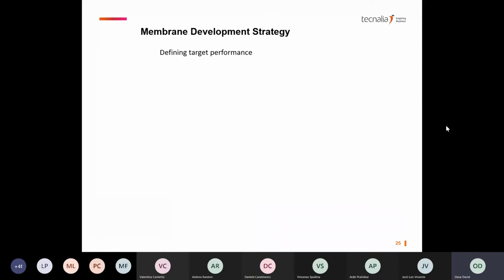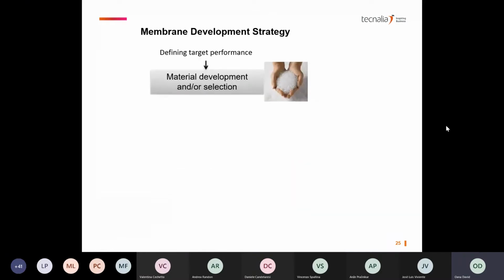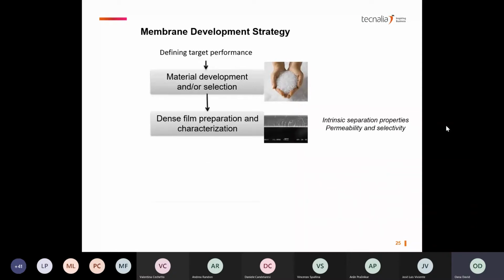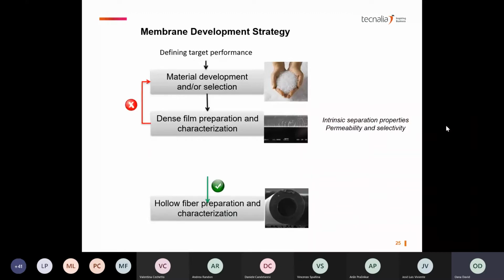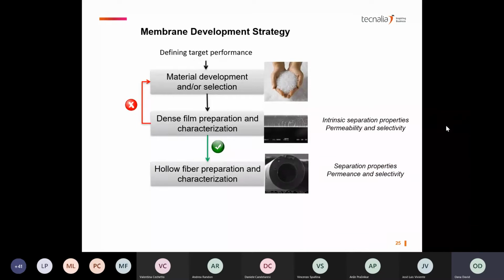As I said, we start with a target performance. We either select a material based on the literature, if there is an available material, or we develop one, like in the Biopolymers project I was mentioning. Then, first of all, we make homogeneous dense film membranes in order to determine the intrinsic separation properties of these materials. If we like them, then we start making an asymmetric hollow fiber membrane. And in order to develop a hollow fiber without defects, we have to do several trials. So we have to optimize the hollow fiber fabrication process.